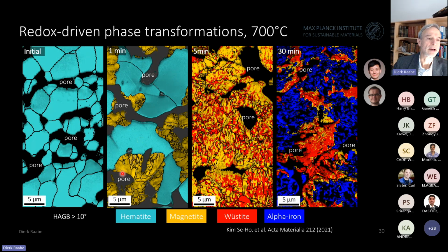And the nucleation rate then depends on the available surface to volume ratio, essentially. And then you can see, however, that the next step, namely the formation of the cubic wüstite in the likewise cubic magnetite, is more complex. And I'll show you some more slides about this topic because it's really, really interesting. Because the wüstite and the magnetite are sharing the same O2 oxygen minus lattice.